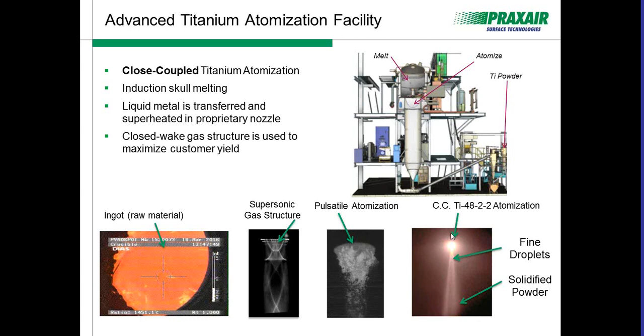When we look at it live time, this is close coupled gas atomization of titanium aluminide. This is the 4822 alloy. What we see here is that flickering. That flickering is real, and what's happening there is it's going through those two stages of flowing and then choked off, and so it's taking advantage again of that primary and secondary atomization. And controlling that pulsatile frequency is key to controlling the size distribution. Again, this is close coupled atomization of titanium, which we were very excited about bringing to the marketplace, because it does allow us to maximize the yield of that type of powder.